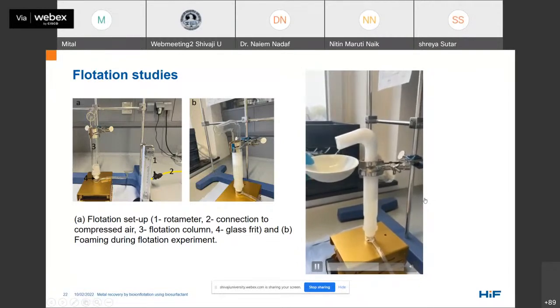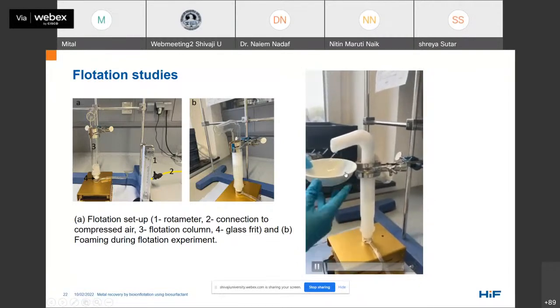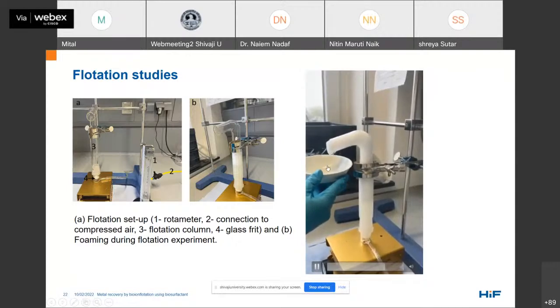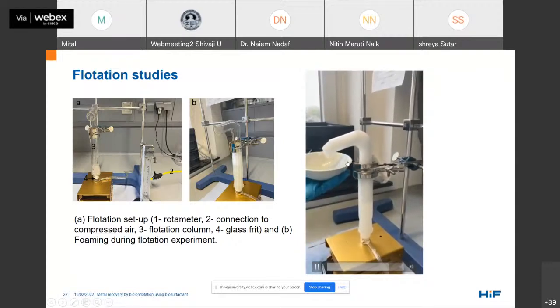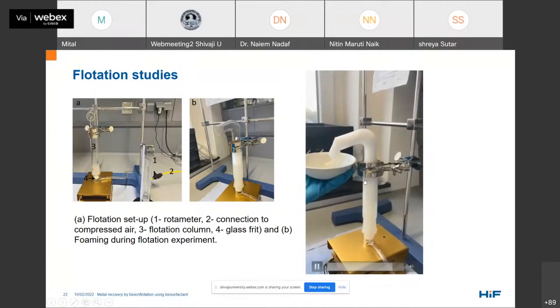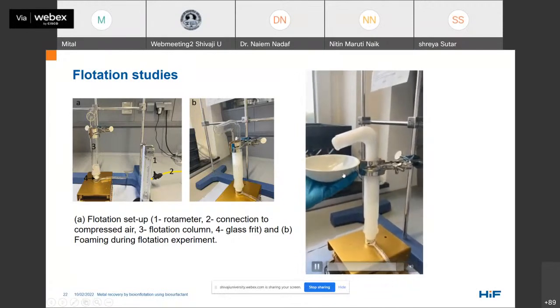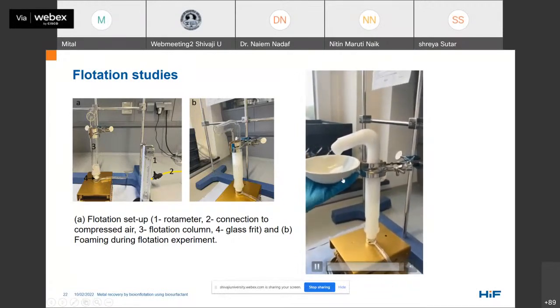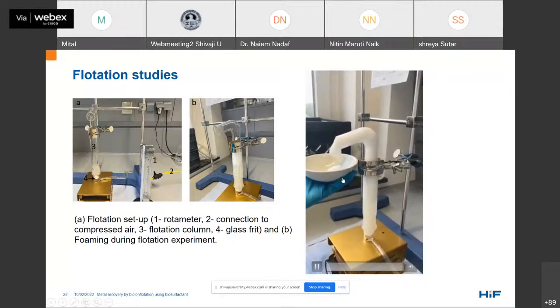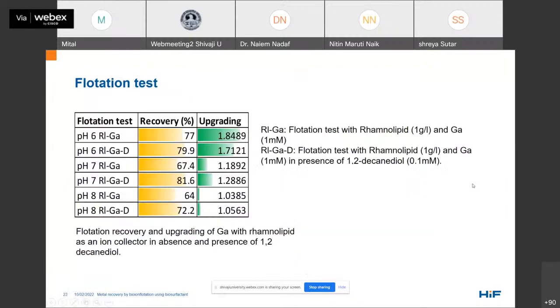concentrates that are collected. Once this foam is collected in the evaporating dish, we break the foam and collect it in small tubes. We measure the volume of this liquid, and then we send it for ICP-MS to know the metal ion concentration. And from this, these are some results from the first few flotation tests which I did earlier.